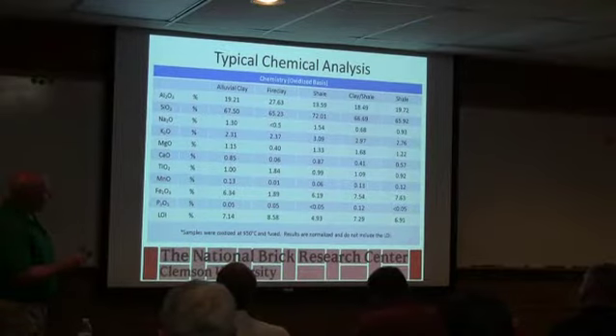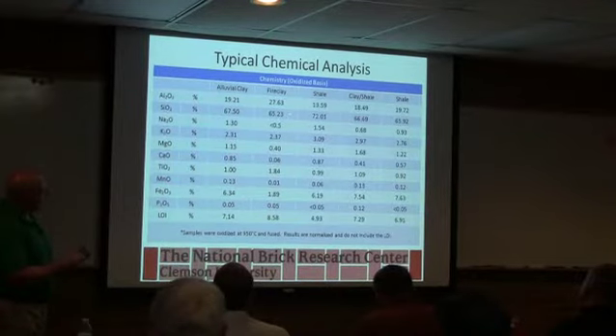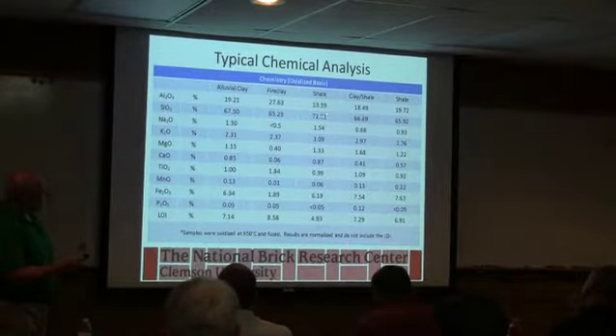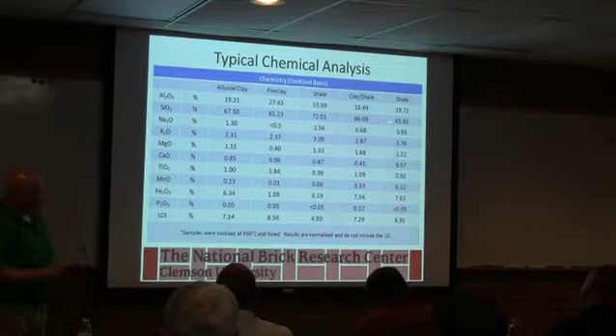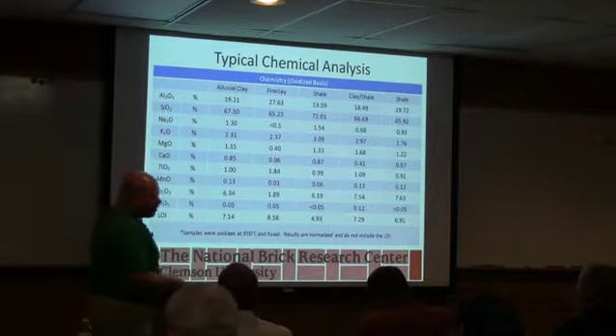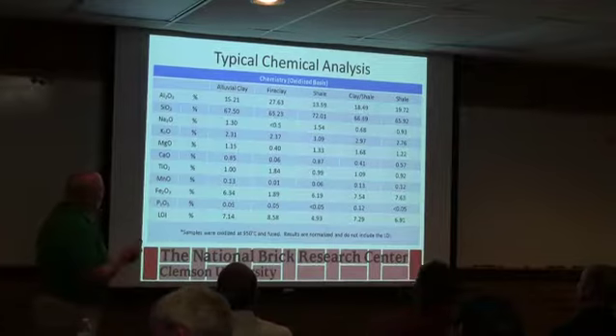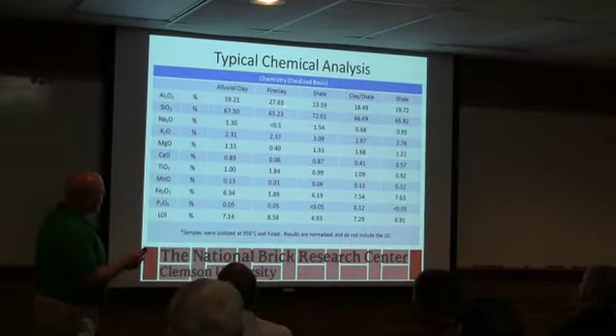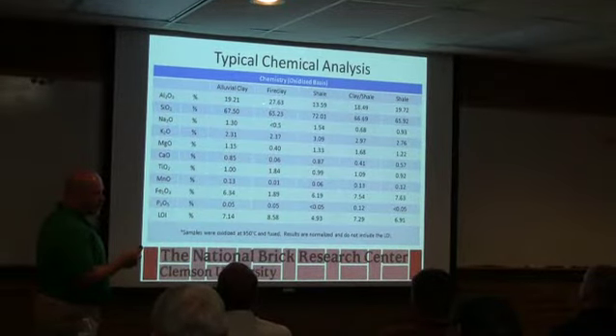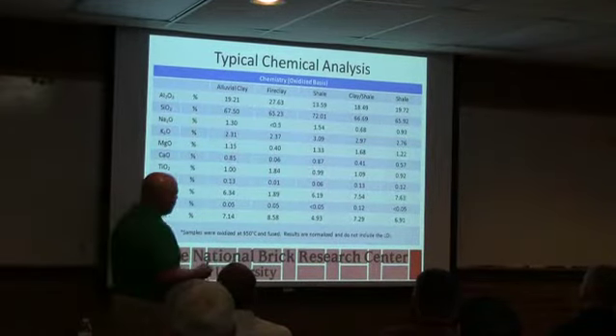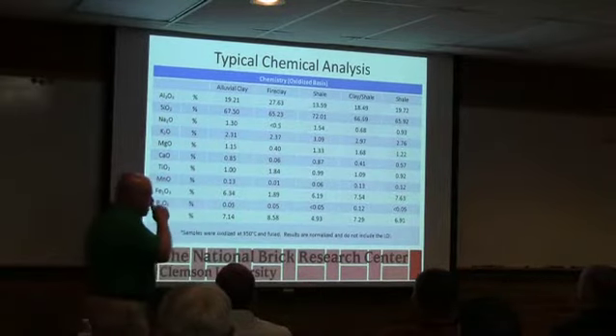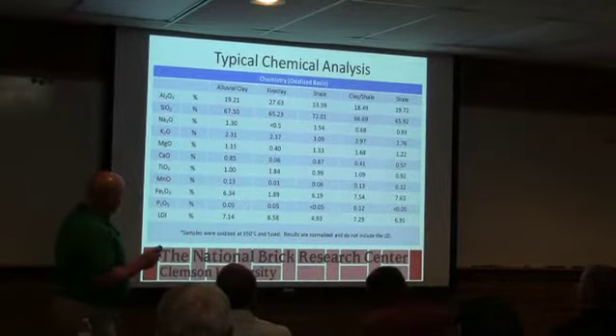But you'll see in all these materials from around the country, there's sort of a range that we typically see here on the silica number. This one's probably getting a little bit on the high end, but usually we're seeing that number somewhere in the 60s. And I do a lot of chemical analysis, and it's always surprising how similar these things are. One of the things, that clay fraction usually kind of tracks with this alumina number, okay? The higher that alumina number is, usually the higher the clay mineral, okay? So they tend to be a little more plastic sometimes. Not always the case, but it's a good indicator.